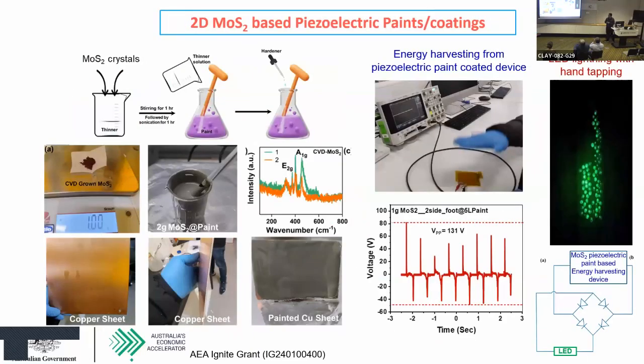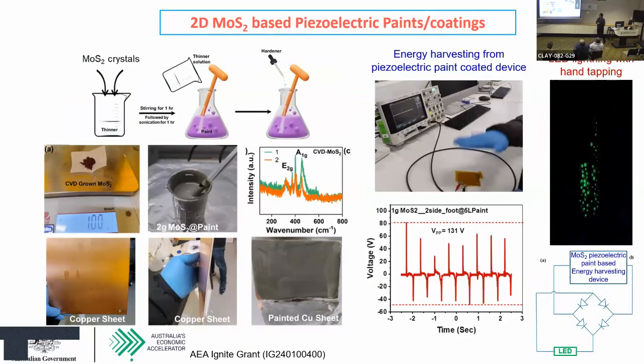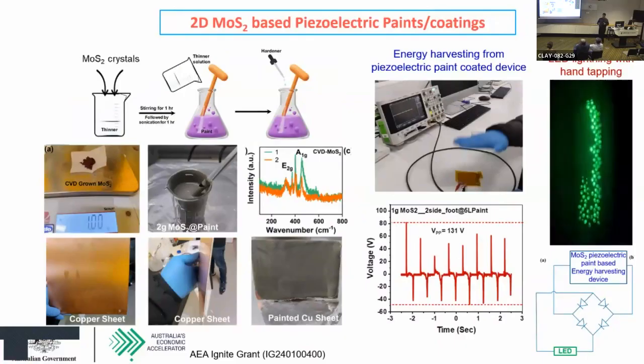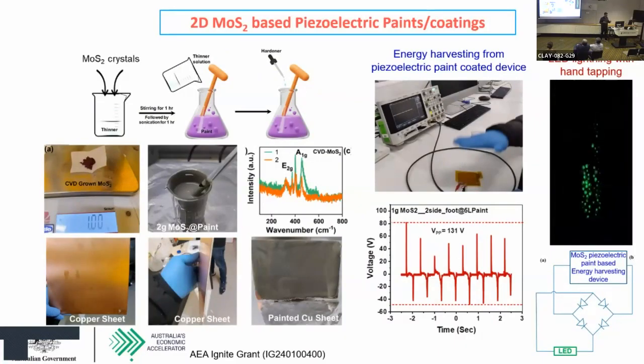We used this for one of our projects with AEA. We used MoS2 in a paint matrix, and this composite is used as piezoelectric paint or piezoelectric coatings. We can harvest energy from it, and also use it for smart structures. We can use these piezoelectric paints for this kind of application.